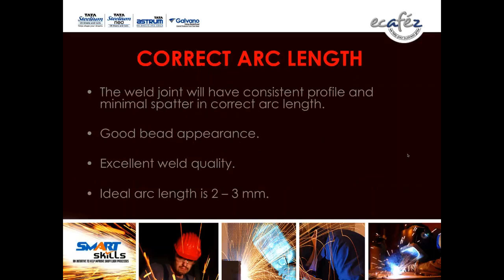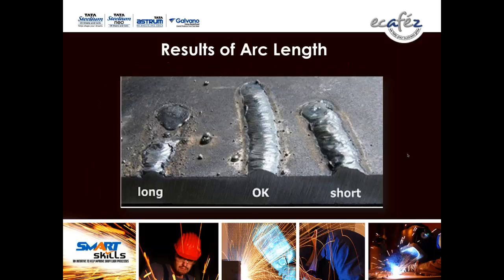If your arc length is correct, the weld joint will have a consistent profile and minimal spatter. In the correct arc length, good bead appearance, excellent weld quality. Ideal arc length is 2 to 3 millimeter. Here, long arc length is on the left side, short arc length on the right side, and in the middle is the correct arc length, showing the good quality weldment by MMA process.